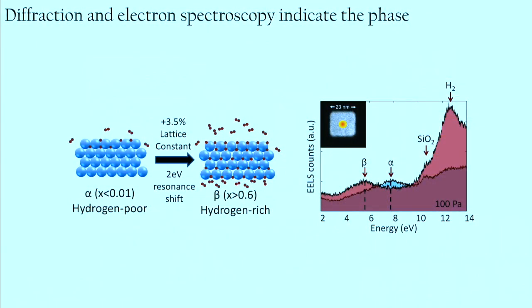So here I mentioned that there is a 3.5% change in lattice constant, so diffraction is of course a very good way of looking at things. And also if we look at the electron spectra or the optical spectra, you can see as you go from the alpha phase to the beta phase, here I've overlapped the two spectra, there's about a 2 electron volt shift in the bulk plasmon resonance. So we can use that large spectral change to follow locally what the phase is.